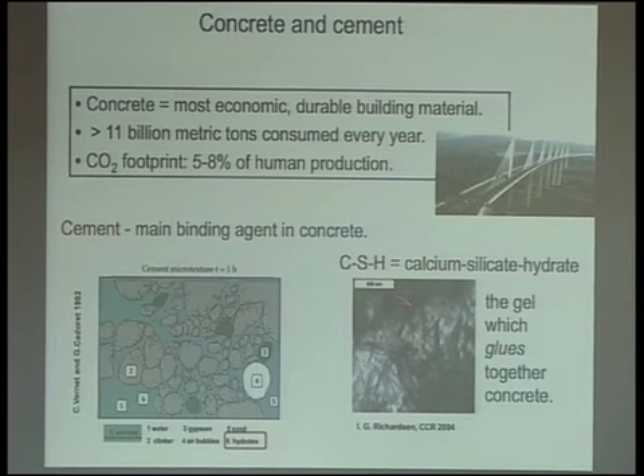The most interesting, maybe I'm a bit biased, but it's objectively true that the most important of these hydration products is what is called CSH in the cement jargon, that is calcium silicate hydrate. Because this calcium silicate hydrate is actually a very sticky gel that develops during cement hydration and setting. So I think that in most cases people tend to think that the drying of cement is drying, but in fact it's not drying. It's this hydration process that actually takes water and puts it into this hydrogel that develops over several hundreds of nanometers. It's a disordered structure and very, very sticky, that eventually solidifies into a glue that glues together the different parts of concrete.